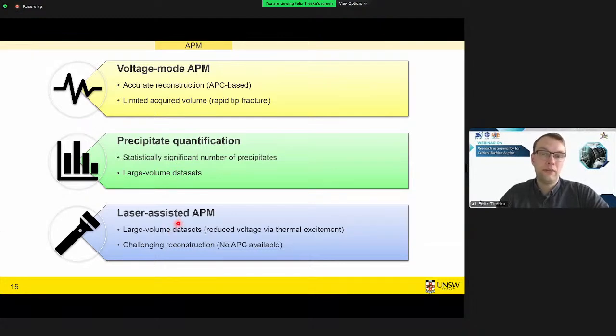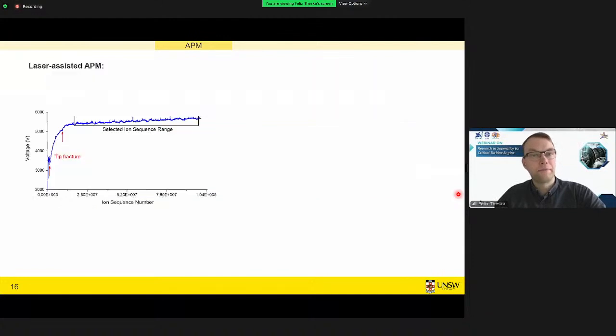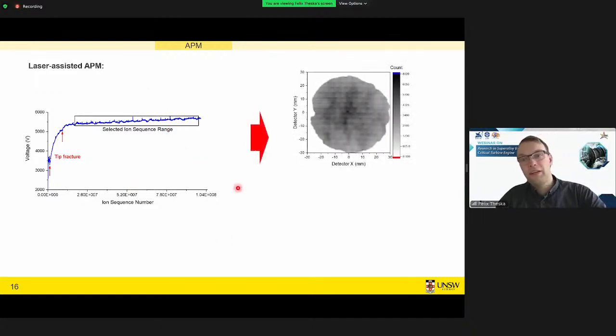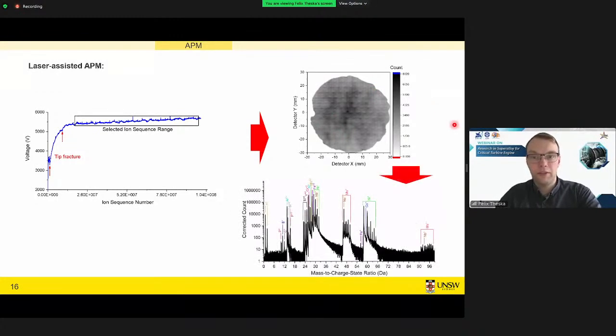And here we can use laser Atomprobe microscopy, where instead of voltage pulsing, we pulse a laser, which requires a lower voltage and therefore less risk of tip fracture. So again, we see a voltage curve like this, and we get more ions. But if we look at the detector map, we see that these crystallographic features have disappeared. That's quite typical for this. The mass spectrum has changed a little as well, but we still can assign all our elements without any problems.